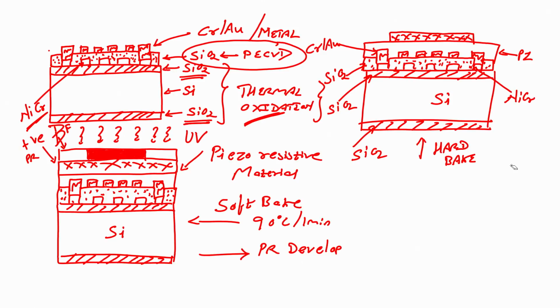to etch the piezoresistive material. So, we have to dip this wafer in a piezoresistive material etchant, right, wet etching. If I do that, what will happen? The piezoresistive material which is protected by the photoresist will not get etched, but the piezoresistive material which is not protected by photoresist will get etched. So, I will have piezoresistive material in this area. All right, you got it, because there is no photoresist that can protect the piezoresistive material